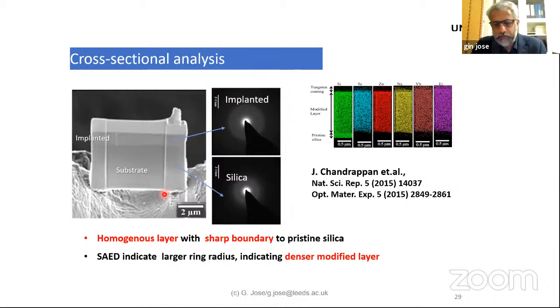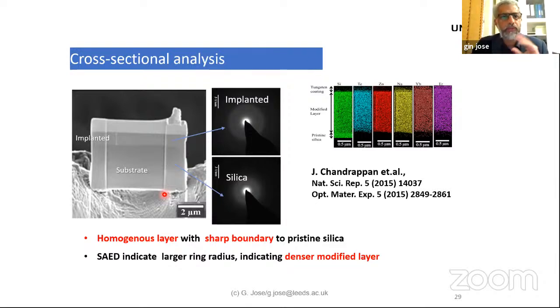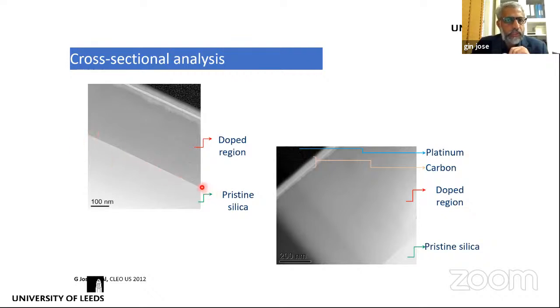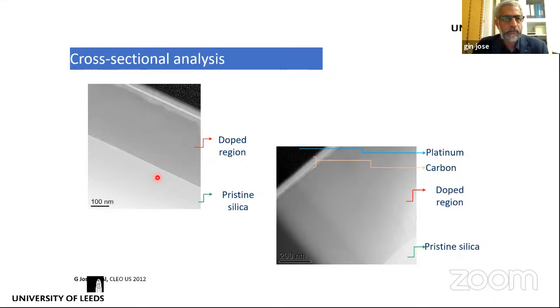This is the key material processing technique developed in our lab for engineering the surface of glasses, polymers, or semiconductor materials for optical, photonic, and other applications. A detailed look at the cross-section shows clearly how the doped layer is different from the original glass, with a very sharp interface between the doped and undoped layers — seen at 100 nm scale using a transmission electron microscope.